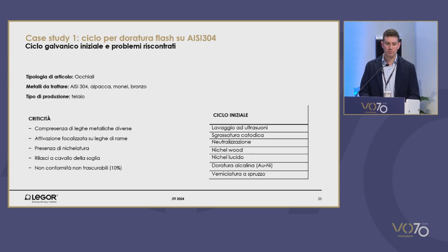This is why subsequent studies were carried out within Legor to develop nickel-free electrodeposition cycles whose objective was that of reducing the nickel release after electrodeposition. In this study, the request that had been put forward by a client in the eyewear industry was very complex. Within the same glasses, there were copper alloys and stainless steel, and basically you have to prepare the surface for that purpose.